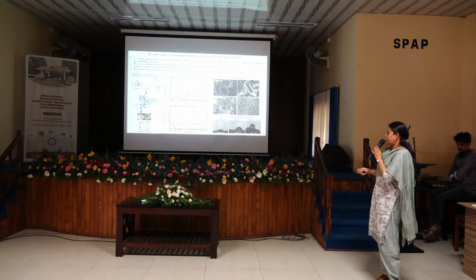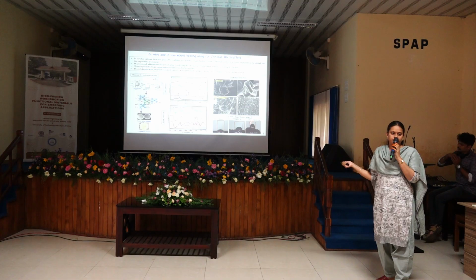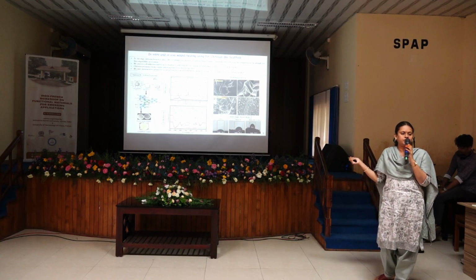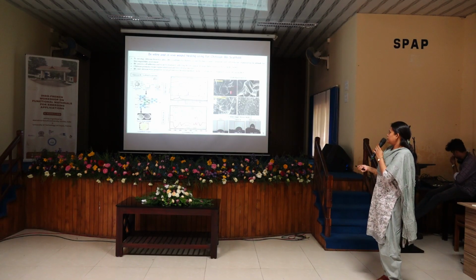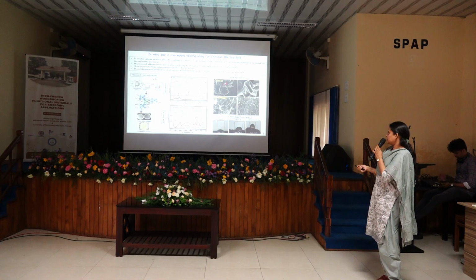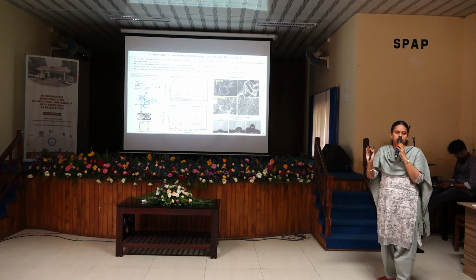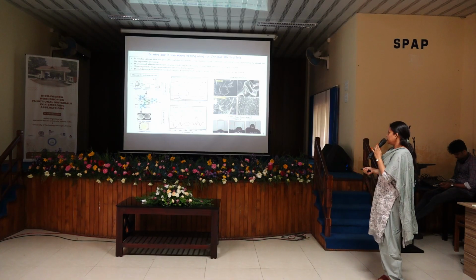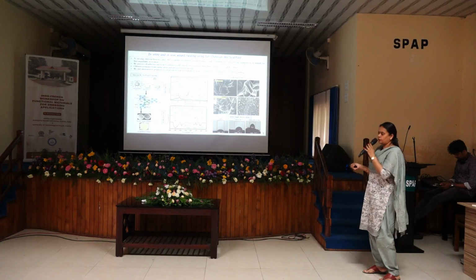Further, with the FTIR pattern, the amide 1 and amide 2 NH bonding of chitosan were majorly attached to the bioglass of silica and calcium. The FESEM result shows chitosan as a sheet, with the BG incorporation deposited like a layer on the chitosan sheets. In the contact angle, the chitosan has shown hydrophilic and the others have shown hydrophobic properties.